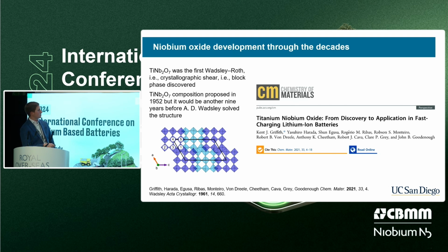As you can see, its components, highlighted here in different colors, are basically corner-shared octahedra that connect together to form a block. If you're familiar with crystal chemistry, you'll recognize that internally this looks a lot like the empty perovskite structure, or the ReO3 structure. But even if you're not a structural chemist, what's interesting is that we have open channels internal to the block, and then at the edge of the block, or the periphery here, we have a condensed shear plane. This is what provides the structural stability.